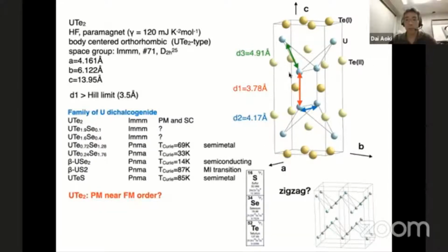And the distance of the first nearest neighbor uranium atom is here. This is 3.78 angstrom, which is a bit larger than the Hill limit. So we can naively expect a magnetic order, but in fact it doesn't show magnetic order. But if you dope with selenium, it shows ferromagnetic order. However, the crystal structure is different. This is PNMA. By the way, this is the same space group as uranium rhodium germanium, or uranium cobalt germanium. Well, anyway, from this we can naively think that uranium ditelluride may be located in the proximity of ferromagnetic order.